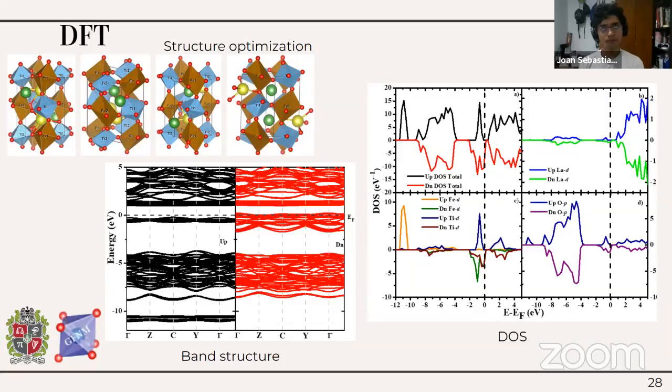And Professor Deluque used a mesh of K-points in the reciprocal lattice following the scheme made by Monkhorst and Pack, with a mesh of 7 times 7 times 5. The calculations were performed following the generalized gradient approximation, and the exchange correlation energy was studied by the Perdew-Burke-Ernzerhof scheme. And in particular, given that we were working with iron, we added a Hubbard correction of 5.3 electron volts to the orbitals of the iron cation.